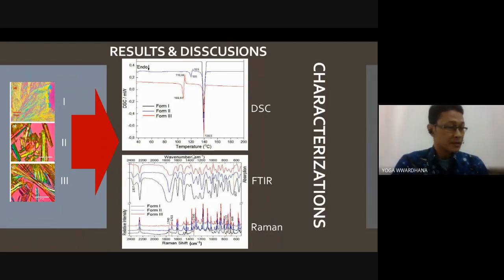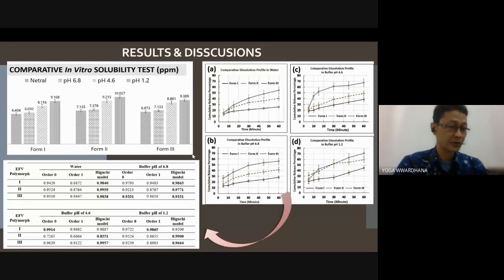Next, since most drug molecules are ionizable, the ionization state plays an essential role in the bioavailability rate limiting step. We found from the vibration spectrum that forms 2 and 3 are more detectable in Raman spectroscopy than FTIR; the IR spectrum indicates that the metastable forms have more polarizability potency than the stable one. Comparing the solubility of each selected efavirenz polymorph in various in vitro media proves that the highest solubility in each medium is form 2, followed by form 3 and 1. The result tells us that the metastable forms are more soluble in those media because of dissociation ability differences.